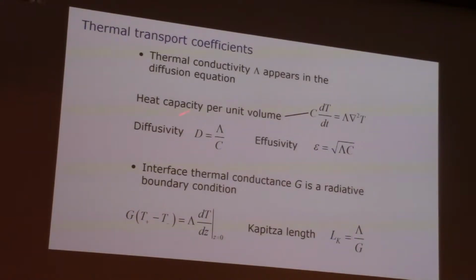Okay, so thermal conductivity is important because that's what appears in the heat diffusion equation. My favorite differential equation, which has in it the heat capacity per unit volume, and the thermal conductivity times the Laplacian of temperature, and one derivative of temperature with respect to time. I can also talk about the ratio of those two. That's the diffusivity. I can take the product and take the square root. That's the effusivity. You're probably familiar with diffusivity, which has the same units as mass diffusion, length squared per time.